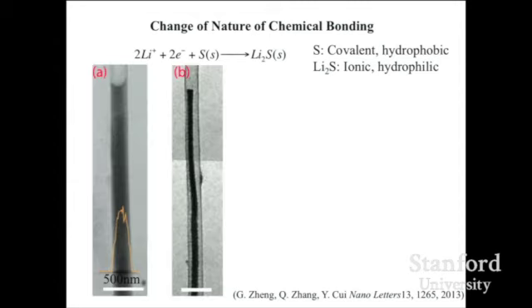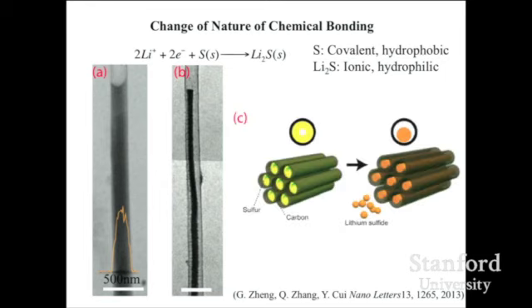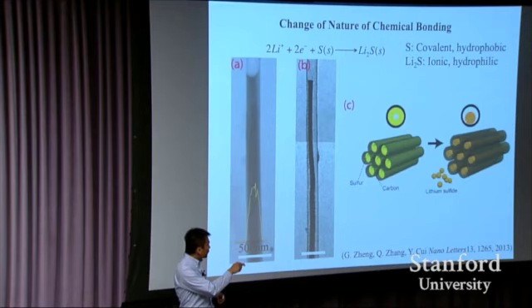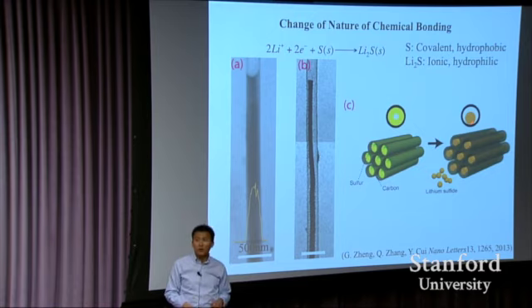So then we looked at this in detail and saw what's happening. Once Wesley started to show me this image, this became very clear. This is sulfur embedded into a hollow carbon, in transmission electron microscopy. Once you put lithium in, you start to see sulfur kind of bead up, become a rod. They detach away from the sidewall. It turned out sulfur likes to wet carbon right here, but lithium sulfide is ionic bonding. Sulfur is covalent bonding. That's freshman chemistry right there. The bonding is different. They like different stuff. Carbon likes sulfur, but carbon doesn't like lithium sulfide. These will come up, and then the polysulfide is so hard to trap. And then the lithium sulfide might be detached away from the sidewall. Electron transport becomes hard. Remember, we need electron transport, we need ion transport. If one thing is screwed up, then you are done, so your capacity will decay.